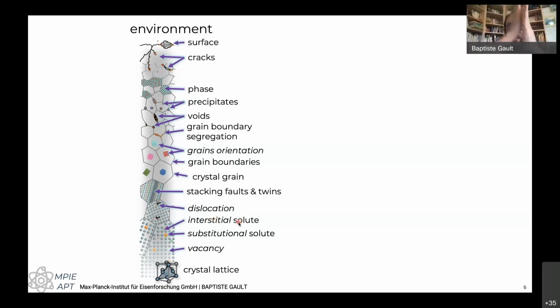So sometimes you have an additional line of atoms, a plane, an additional half plane, like a dislocation somewhere. This can also happen when you're starting to deform the sample. You can have just the lattice twisting like this or forming these twins. And then the crystals of the crystal lattice can have different orientations with respect to each other, which is also going to affect the material's properties. And then some of these foreign atoms can segregate to the boundaries, or they can be voids. And then you keep going like this.